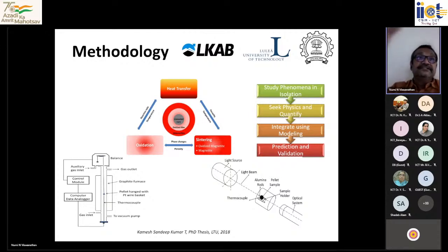So then we said, let us look at it more quantitatively and more scientifically. In science, whenever you have a complex system, first you identify the important phenomena which govern the system or influence the process. In this case, as I told you, it's magnetite, which gets oxidized to another form called hematite, Fe3O4 to Fe2O3. So there is an oxidation process involved, and there is sintering: this pellet is made of very fine powder particles, and these particles form bonds because of high temperature, again with fundamental processes involved. They form bridges between them, and that gives them strength; that is called sintering. And on top of it, there is heat transfer happening inside the pellets.